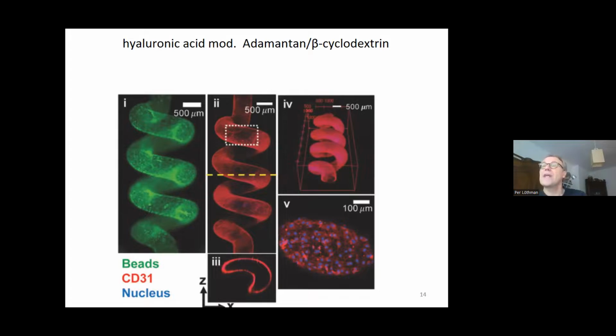What we see here is a shear thinning and self-healing bioink based on supramolecular self-assembly through guest host complexes. In this case, it allows for continuous printing in any direction of 3D space and seeding also with endothelial cells. As I said, hyaluronic acid was modified with adamantane or beta cyclodextrin and mixed. In this particular case, the mechanical properties of the bioink could be modulated by varying the degree of chemical modification.